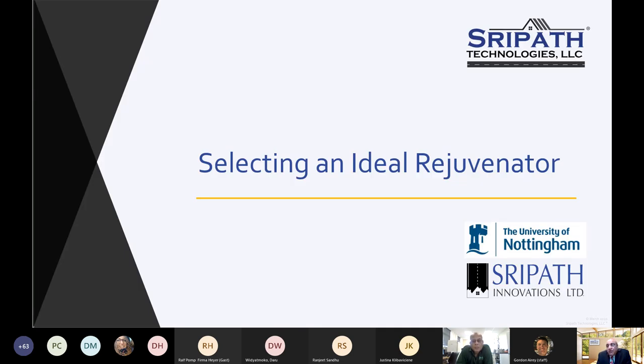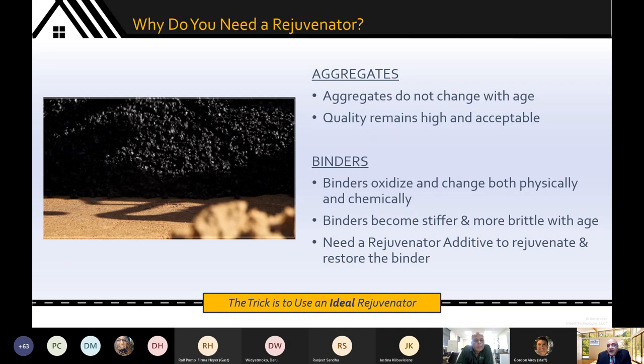So we walked through how to make a mix design for the lab. The question now is, how do you pick a good rejuvenator? And before you do that, let's ask the question, what is it in the RAP that is really changing from a virgin mix? It is well acknowledged that aggregates do not change. And so if you had an aggregate that was compliant with specs, let's say 5 years ago, when you put down the road, and it could be a simple LA abrasion type test or other tests that you use, chances are very good that it is still acceptable for use on the roadway.